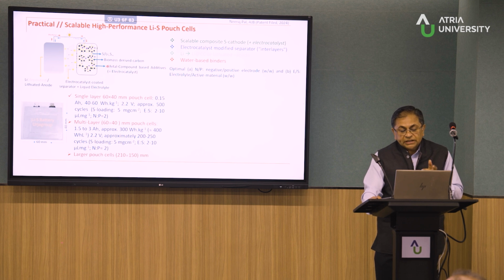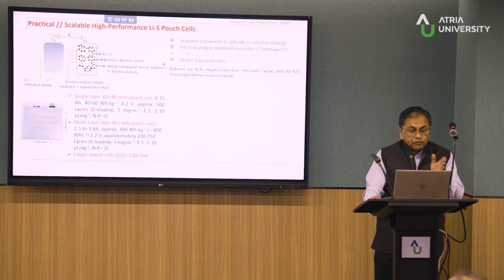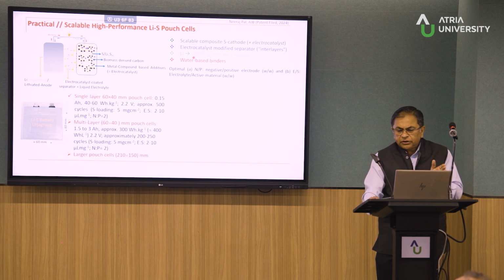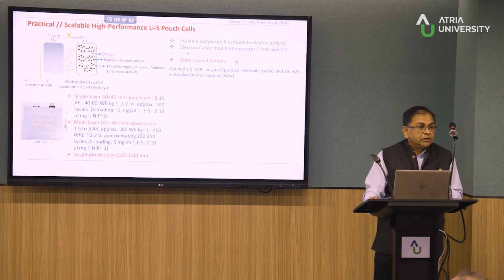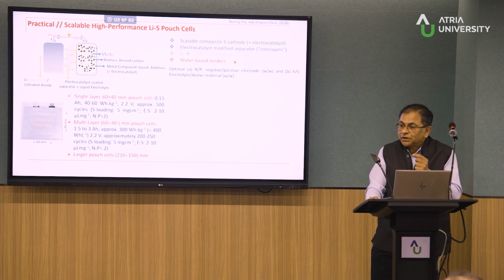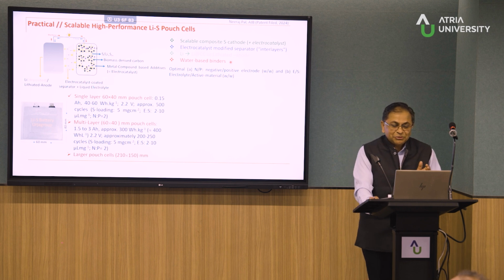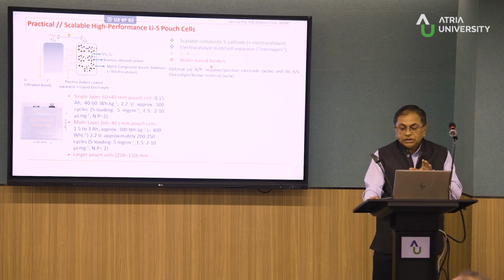Firstly, you generate a very scalable composite sulfur cathode plus an electrolyte and electrocatalyst. And we again invoke the concept of interlayers here. I'm not going to talk much about it because most of our work right now for the pouch cells has been with lithium metal. But we plan to shift to lithium coated on a copper current collector. The problem is importing. We have to import this product from the United States, which is a huge amount of money. And we're actually using water-based binders.